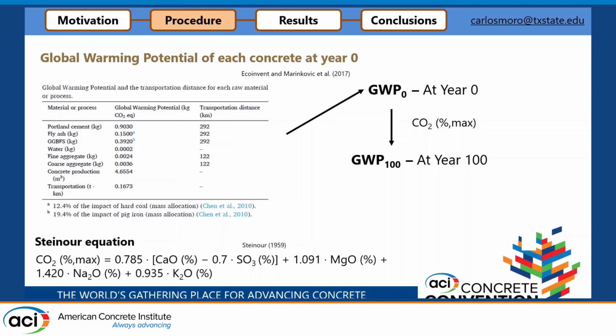That means their theoretical maximum CO2 uptake, which is basically also what the other speakers were speaking about, is based on this formula right here, that I'm not going to explain, but it's the Steinour equation that basically tells you, with the composition of your cement or your cementitious materials, what is the maximum that you can take. That is around 50%, as we were also speaking about. So at year 100, we're assuming that all the concretes are going to be completely carbonated. I think that is a realistic assumption, right?